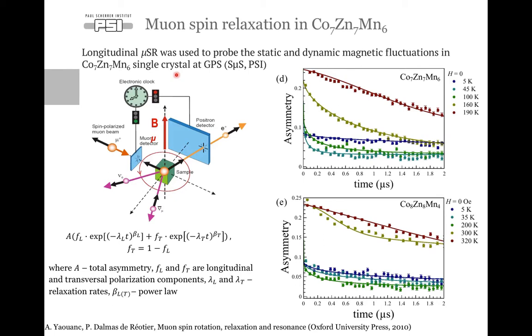So this is slow magnetic fluctuations that are hardly accessible by any other probe, such as neutron scattering, inelastic neutron scattering, or inelastic X-ray scattering. In this technique, the muon beam is implanted into the sample with a penetration length of 100 or 200 micrometers, so it's actually bulk sensitive. Then the muon decays inside the sample and emits a positron and two neutrinos. And the direction of the positron emission actually depends on the direction of the muon spin.